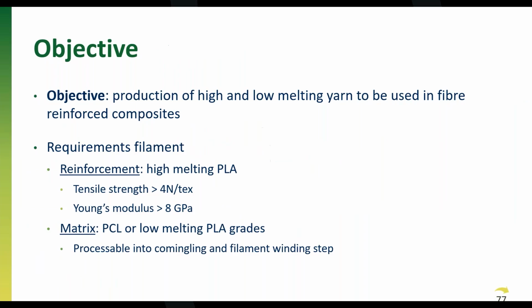Now, the objective here for Centexbel was to produce high and low melting yarns to be used in fiber reinforced composite materials. Of course, the high melting yarns will be the reinforcement yarn in the composite because we will not melt them. We have some specifications for that: tensile strength of 4 Newton per tex and a Young's modulus over 8 gigapascal. For the matrix yarns, it's either PCL, which has a very low melting point of around 60 degrees, a little bit lower, and then some low melting PLA grades where we have some more flexibility towards the melting points. No mechanical properties here that are necessary to achieve, only that the yarns are processable within the next production steps. So the filament winding, the commingling, the weaving, etc.